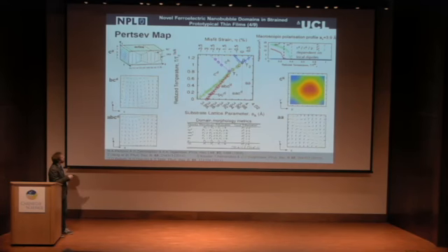But then we also found these CB domains, which, as far as we could see, hadn't been observed for these PTO thin films. So here we are, we call them CB because they're C domains, they're in and out of the plane, this is from the surface, but they're kind of bubbles rather than being tubes like they are here.